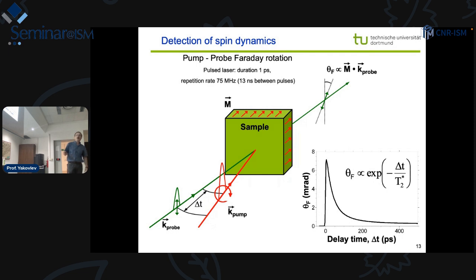It's pump-probe where the pump is circularly polarized. So this pump photo-generates spin-oriented carriers. And then we use the Faraday effect to test this spin polarization when we send linearly polarized light. And you know that if you send linearly polarized light through a magnetized medium, the polarization plane will rotate. Actually, we measure the rotation of this plane, and we change the time delay between pump and probe pulse. So the duration of the pulses is 1 picosecond.